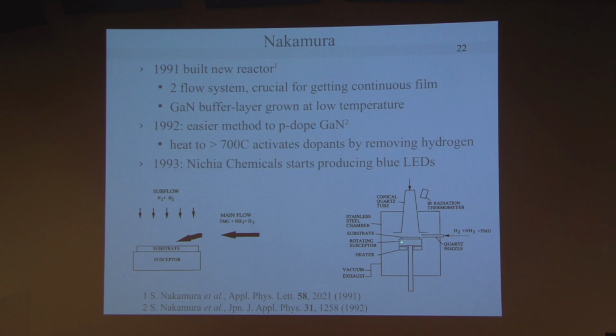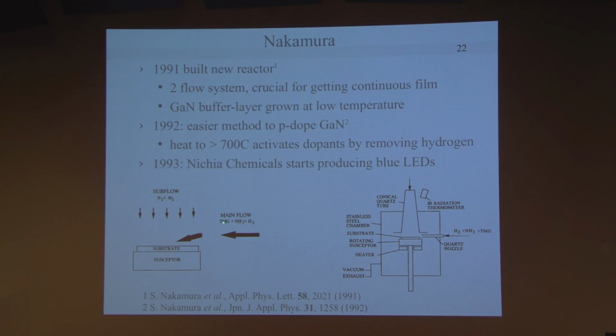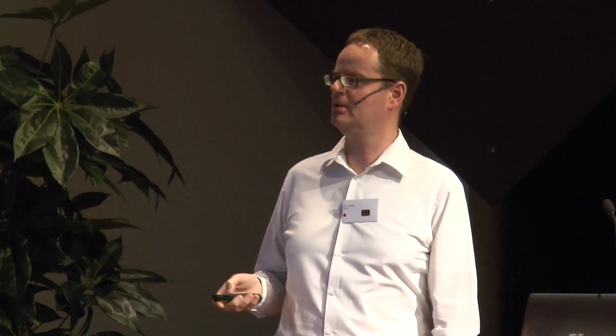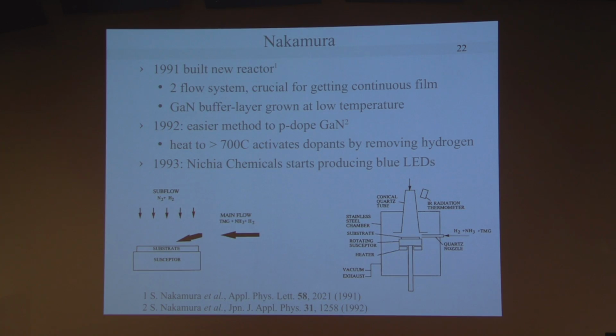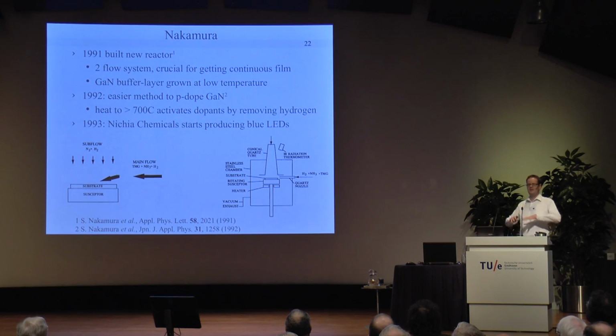So he has a substrate, and he actually has two inlets for the gas flow. It's also shown here on the left, he has a main flow that carries the trimethyl gallium and the ammonia, components of gallium nitride, if you will. And he found that he needed a subflow to gently push the reactants onto the substrate to make the growth happen. And this, he claims, is very important. Without that second flow, he did not get a nicely continuous film. He got small islands of gallium nitride.